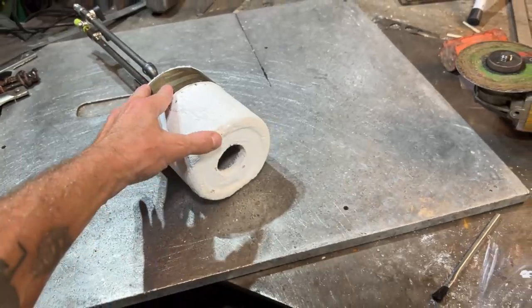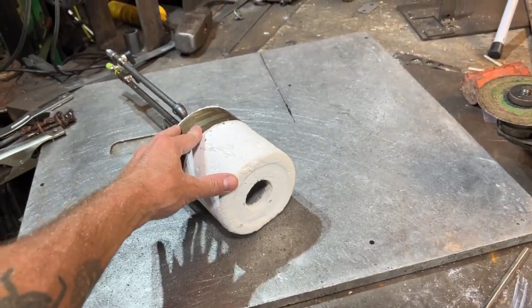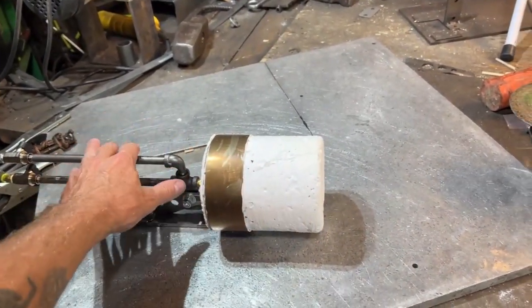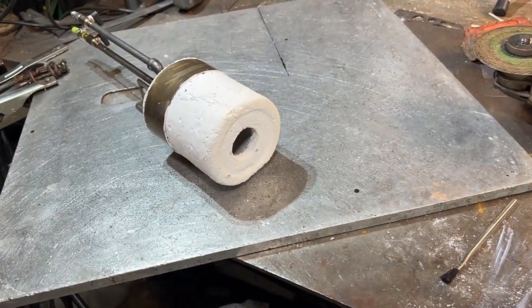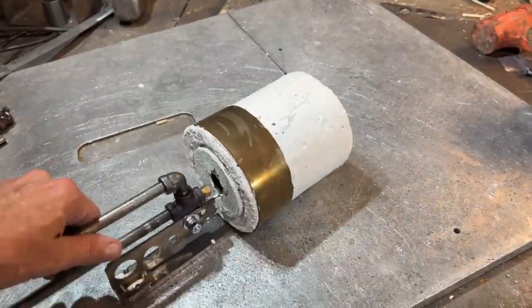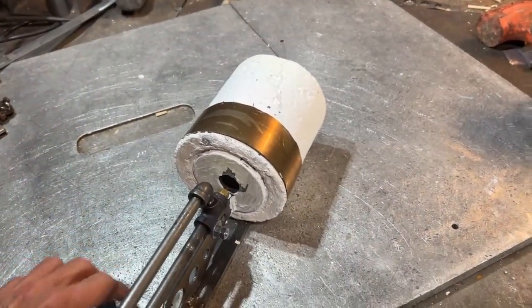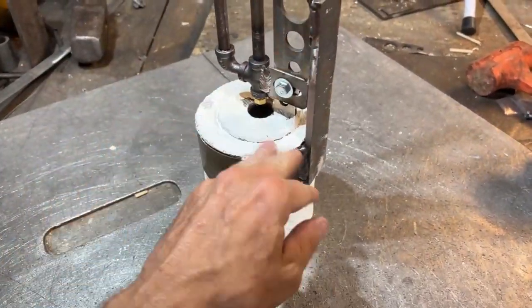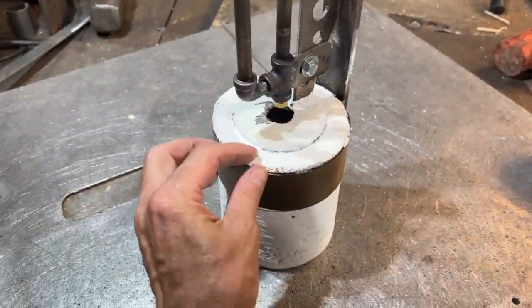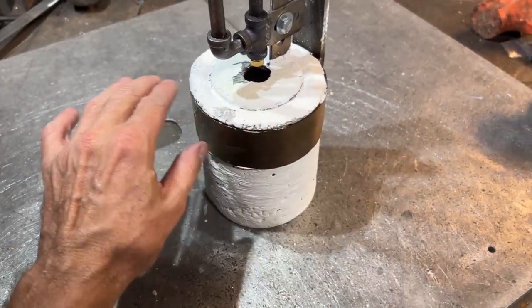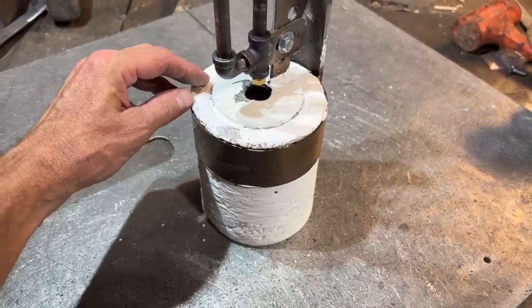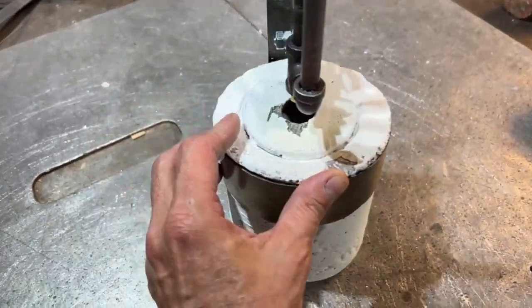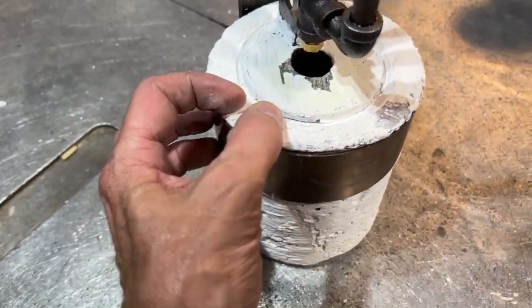When this burner is in operation it will be stuck in the side of a wall of a furnace, so a crack like this isn't going to really do anything at all, not going to hurt us. Tomorrow we're going to test this thing on waste oil. And the coating did not hold up as well as I wanted to, I'm going to have to tweak the composition on that a little bit. I was just giving this yttrium oxide a try.